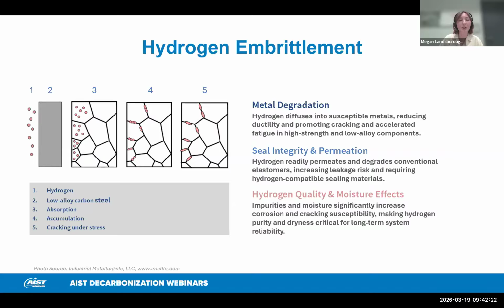So the image that I have here on the left, you can see that this is hydrogen embrittlement. In our first image here would be the hydrogen molecules. And then in the second image, this would be your low alloy carbon steel. In image 3, you see the absorption. So this is where hydrogen molecules dissociate into atomic hydrogen at the steel surface and diffuse into the metal lattice.